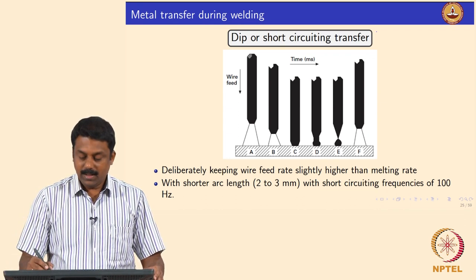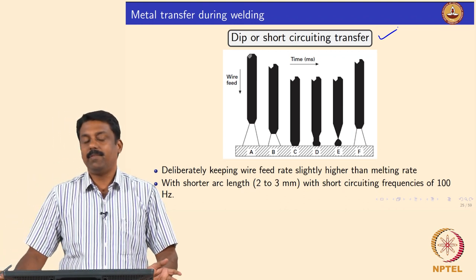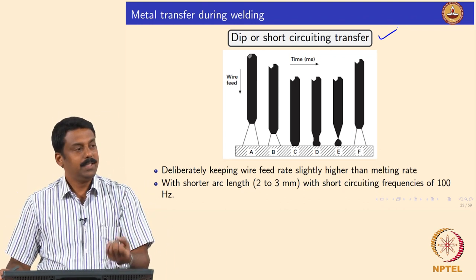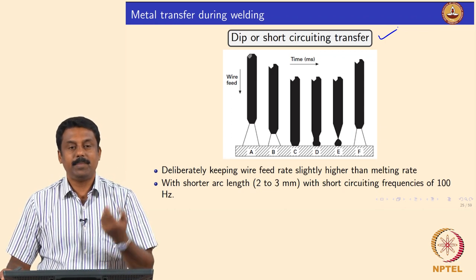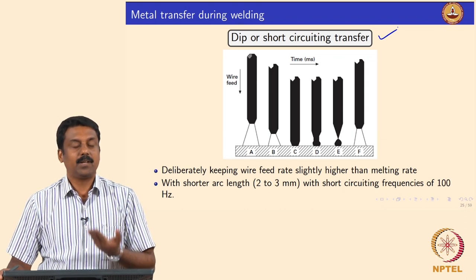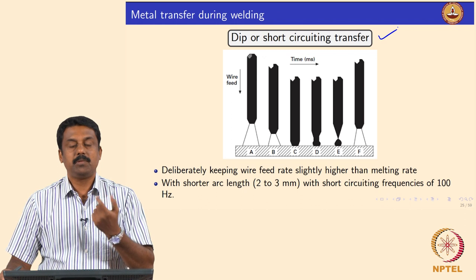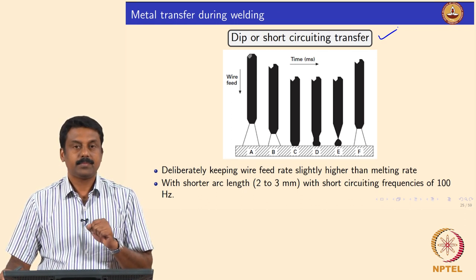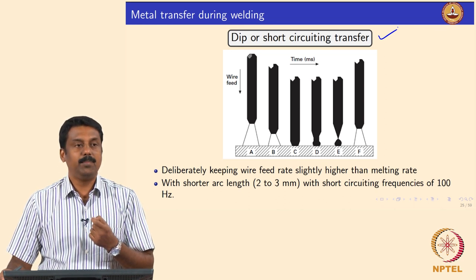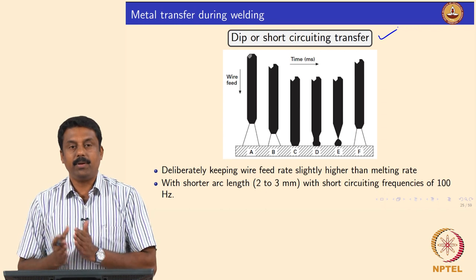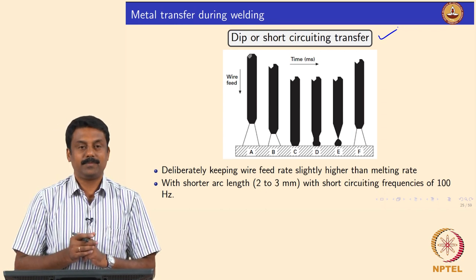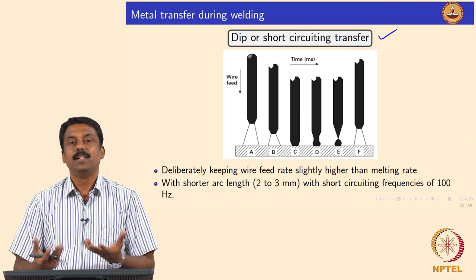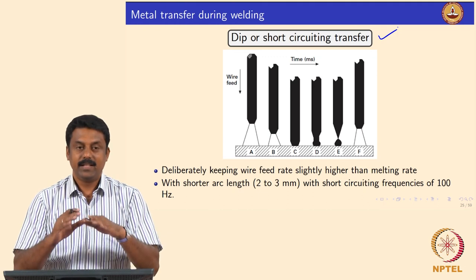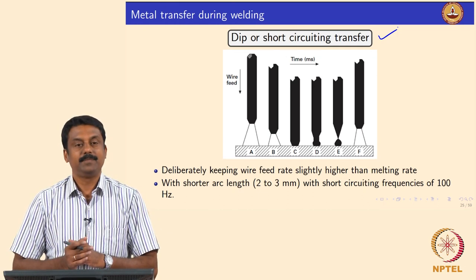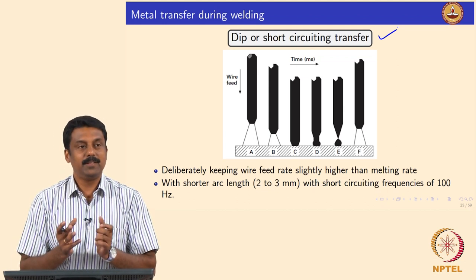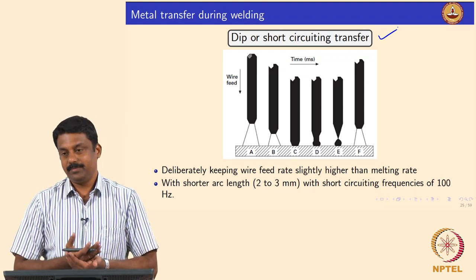This is a part of non-free flight transfer. In free flight transfer, droplets are transported from the tip by free flight, is it not? So, you can also achieve the transfer by short circuiting. There are a lot of advantages of having a short circuiting transfer. One of the major advantages is controlling the heat input. By carefully manipulating the event of short circuiting, we can switch off the arc momentarily, so that when the droplet is transferred, it is transferred by the surface tension of the liquid, no other factor. By doing so, we can reduce the superheating of the pool.